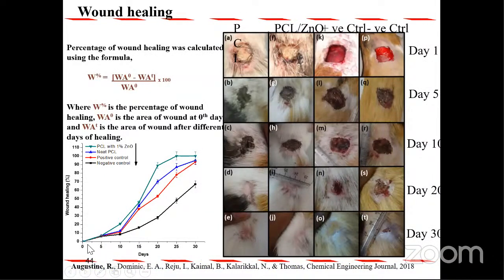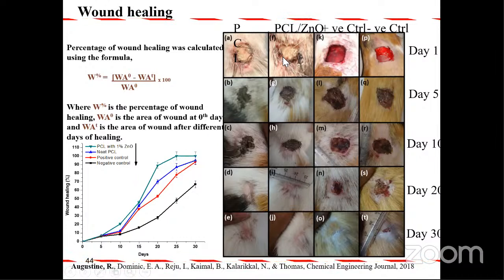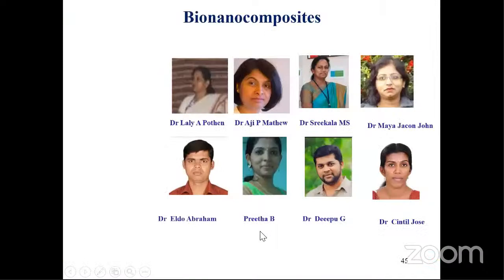Look at the quantified wound healing process, number of days, and wound healing efficiency. The best one was PCL with 1% of zinc oxide. You can see this is 1% of zinc oxide. You see the hair growth. If you don't use zinc oxide, only PCL, you don't see much hair growth. And you see the positive and negative samples. So this is the best, PCL with 1% of zinc oxide. We are also into nanomaterials from agricultural waste.